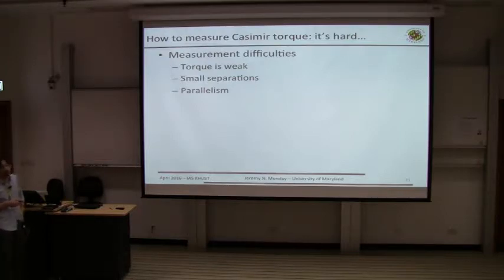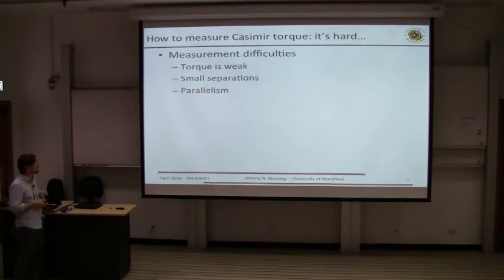And so the torque is weak. So it's an even weaker effect. It's a little bit hard maybe to compare forces and torques, but I would say that they're at least equally hard because of being weak. Again, you want small separations, just like with the Casimir force. And you also have to deal with parallelism. So you want to keep two plates parallel like you do for Casimir. For Casimir force measurements, you usually switch to a sphere-plate geometry, which helps, but that's harder to do if you're looking at a torque.